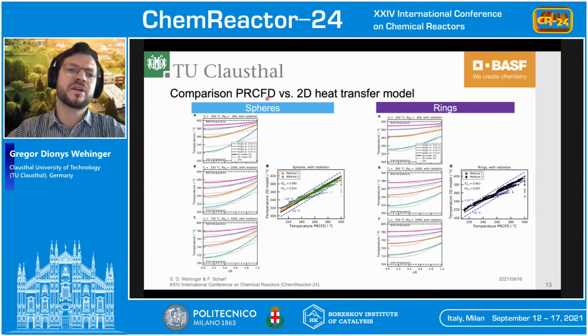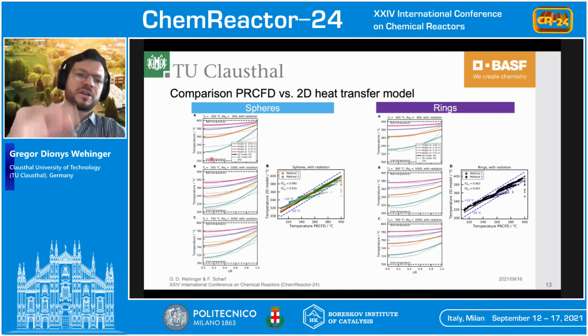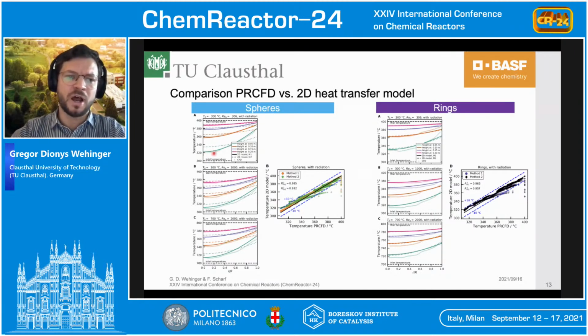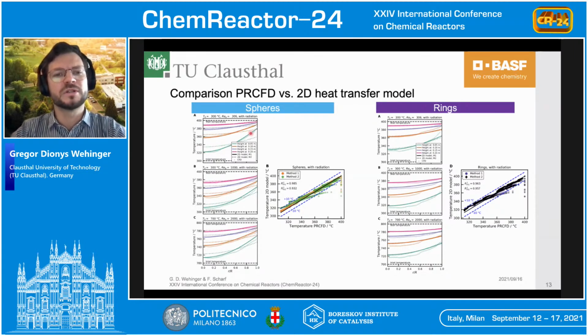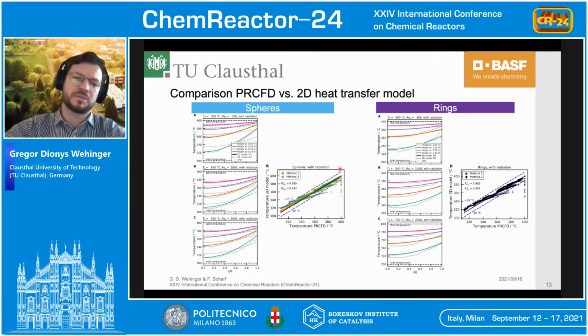Here I really compare the PRCFD results with the 2D heat transfer model for radial temperature profiles at different positions. So the dots are the CFD simulations, and the straight line is the 2D pseudo-homogeneous model with the derived parameters. And as you can see for the spheres, the model with parameters from method 1 looks pretty good. Here on a parity plot, we are really close to the PRCFD results, obviously not very close to the wall, because here we see this temperature jump.